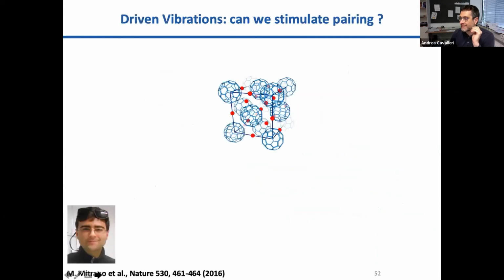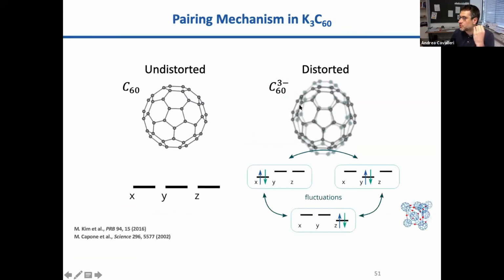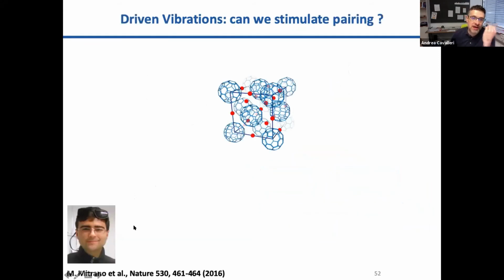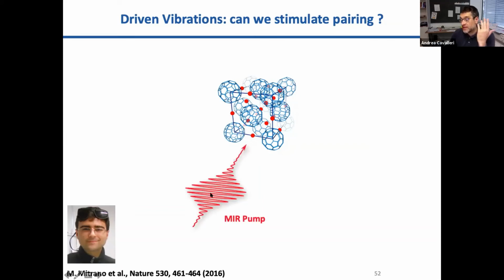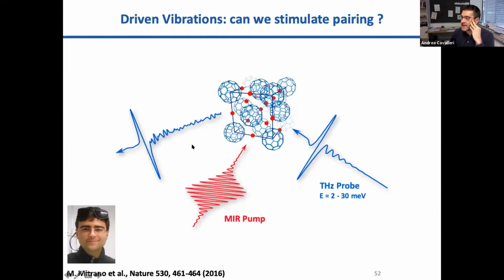And what Matteo Mitrano suggested at the time was that maybe if we use a suitable mid-infrared pump, which can reproduce fluctuations that are the ones that mediate pairing in equilibrium, maybe we can stiffen up the superconductor and enhance Tc. So what he proposed was that he would pump this material with mid-infrared light, and then he would probe with a second pulse in search for the opening of a gap.